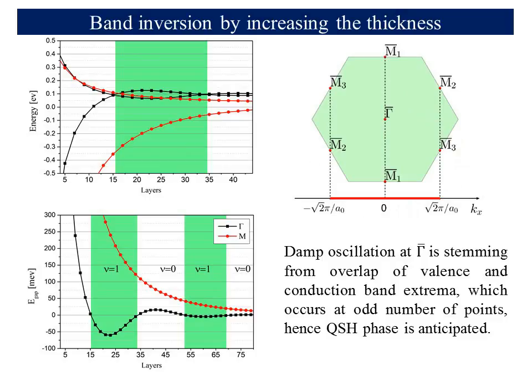As one can see in the figures, nu equals 1 — that is, the quantum spin Hall phase — was obtained for all film thicknesses with inverted band gap, denoted by the green highlighted regions. For example, in a cation-terminated tin telluride film, the quantum spin Hall phase should appear for films 17 to 33 monolayers thick, corresponding to the range of thicknesses from 3.1 to 6 nanometers.